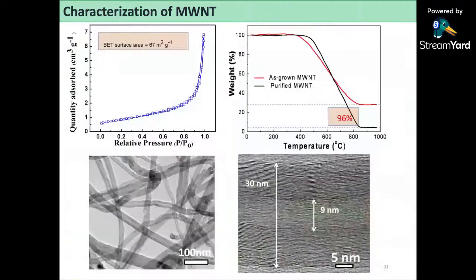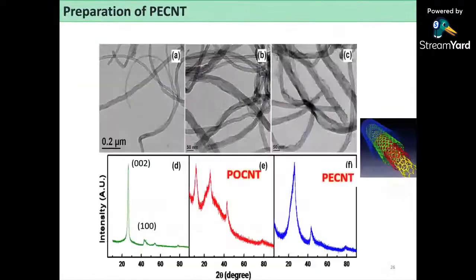I'll show it first, and then I'll come back here. You can see these few layers I cut open. So what happens is that you have the two-dimensional graphene, and then the one-dimensional inner core of the carbon nanotubes, which will give very good electrical conductivity, whereas the outer layers will give more specific surface area.